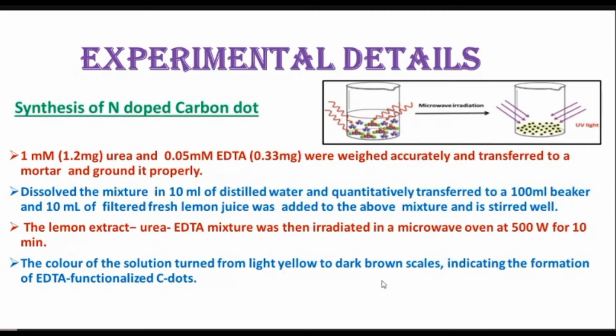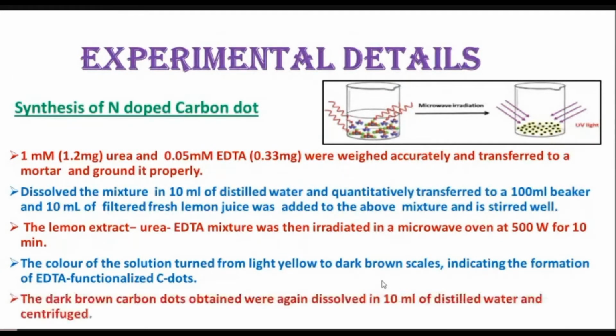Thus, we obtain dark brown scales, indicating the formation of EDTA-functionalized carbon dots. These are again dissolved in 10 ml of distilled water and centrifuged 3 times. The supernatant solution is our synthesized nitrogen-doped carbon dots.